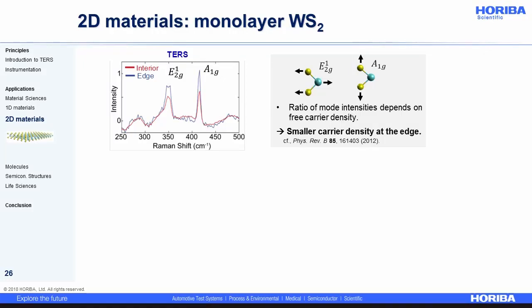The average TERS spectra of the interior and the edge regions are shown in this figure. At the edge, the A1g mode is slightly enhanced with respect to the E2g mode. And this is known to be the signature of a smaller carrier density in this area.